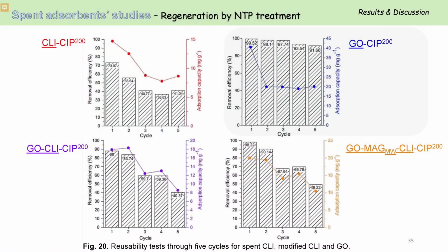First, the regeneration of the spent adsorbents with high clinoptilolite ciprofloxacin loading was performed. High content means that I used the ciprofloxacin solution of 200 ppm for the adsorption. As we can see, for the pure graphene oxide we got the best results. The removal efficiency remained practically constant during the 5 adsorption cycles, while for the other spent adsorbents the removal efficiency gradually decreased with the regeneration cycles. This can be related to the high ciprofloxacin content, partially blocking the pores of the adsorbents with the byproducts of plasma and ciprofloxacin.